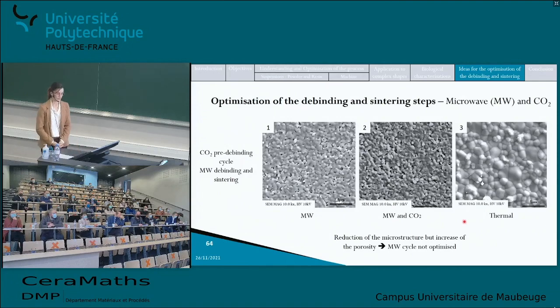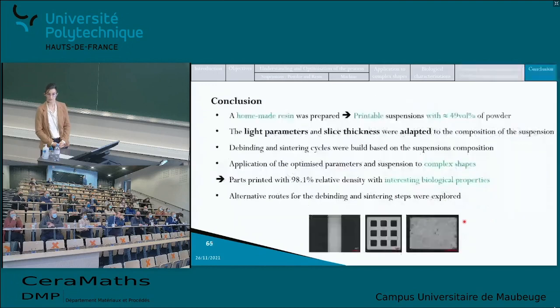So in conclusion, a homemade resin was prepared and enabled us to manufacture printable suspensions with around 49% of beta-TCP powder, which was a high enough solid load. The light parameters and slice thickness were adapted to the composition of the suspension. The debinding and sintering cycle was built based on the composition of the suspension, and all of that could be applied to the production of complex shapes. It also provided parts with relative density above 98% and with interesting biological properties. Moreover, alternative routes for the debinding and the sintering step were explored and gave encouraging results for the pursuit of this work.